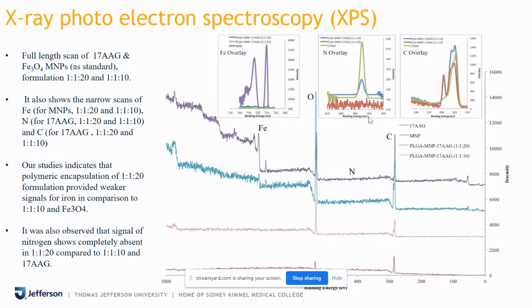So we focused on it. The bottom spectra is a full length scan, and the top spectra is a narrow scan to see what's going on with the Fe, nitrogen, and carbon to understand the story of the polymeric covering. Now, the Fe overlay shows that the standard Fe has 2 giant peaks, confirming that Fe was there. But if you see the other 2 formulations, because of the polymeric cover, the signals were extremely small. On the other hand, because we confirmed Fe was present using the transmission electron microscopy EDX, we were okay that maybe the polymeric shell is actually reducing the signals from Fe, which is coming from inside.